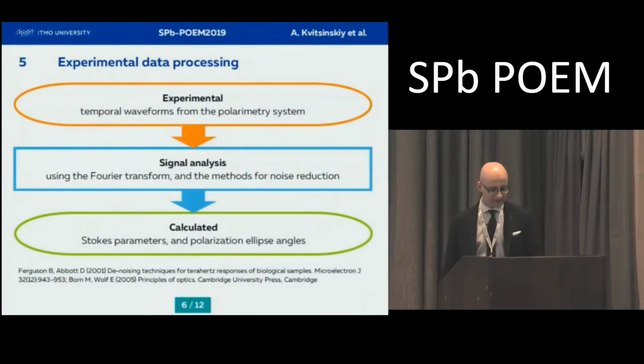Experimental data processing was done using the MATLAB software. A coiflet-based denoising technique and boxcar signal windowing was used in this method. This technique allowed obtaining noise-free spectra in the range of interest. After that, the Stokes parameters and frequency dependencies of azimuth and ellipticity angles of the polarization ellipse of the sample were calculated.